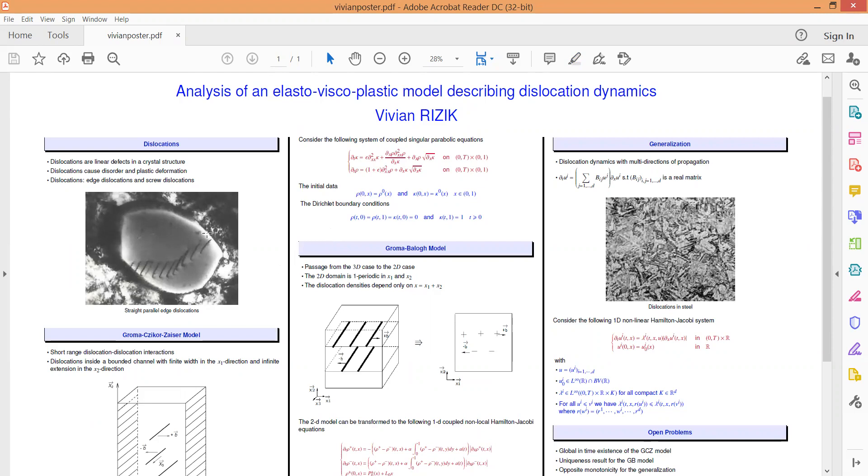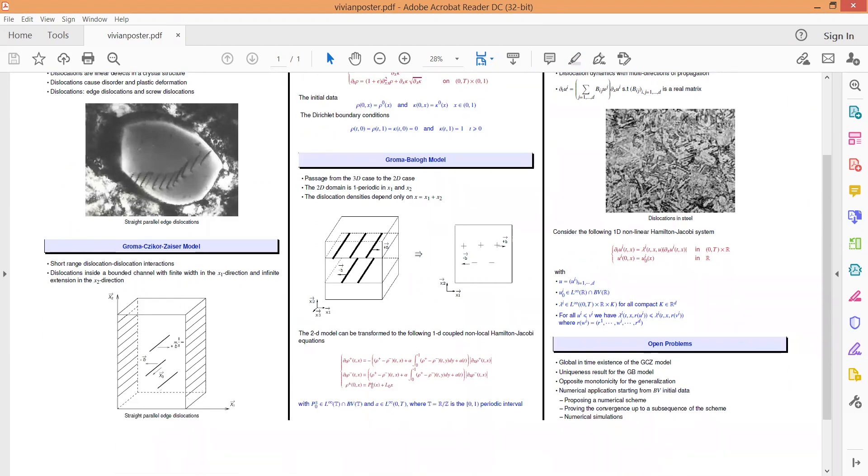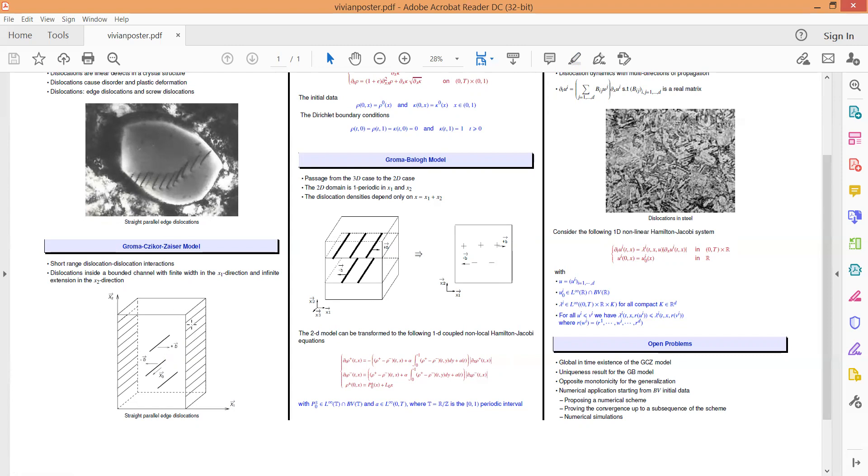Dislocations, presented by these dark lines, are linear defects or irregularities within crystals. They can move when applied to stress fields, and their motion is one of the main explanations for plastic deformation. These dislocations are characterized by two vectors: the dislocation line X3 and the Burgers vector B, presenting the direction of propagation of dislocations. These two vectors enable us to distinguish between two types of dislocations: screw dislocations where B is parallel to X3, and edge dislocations where B is perpendicular to X3.